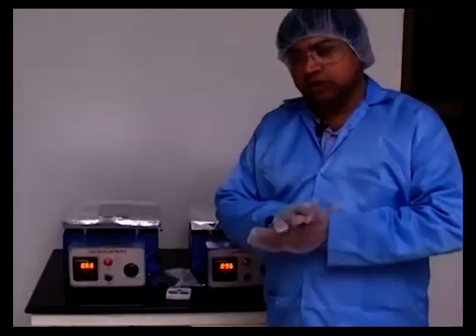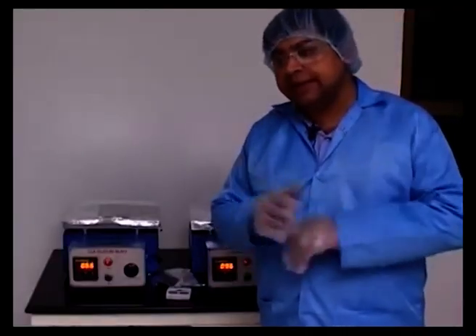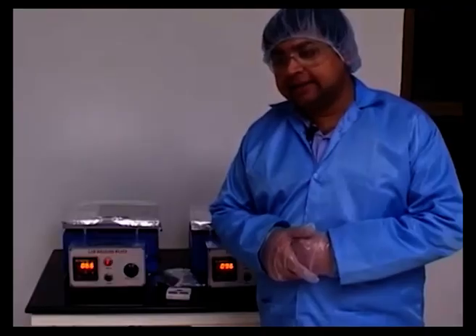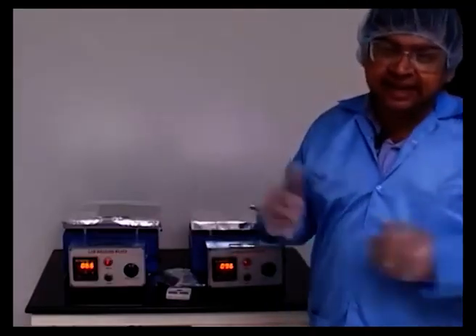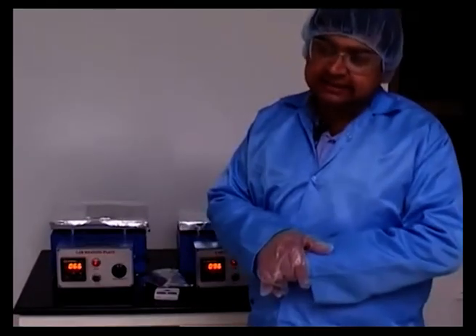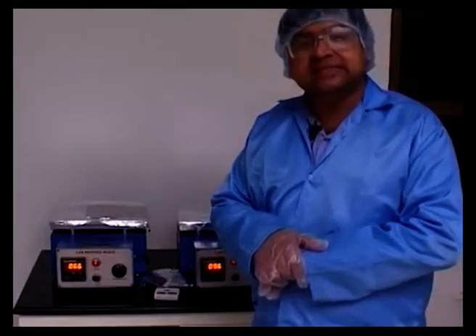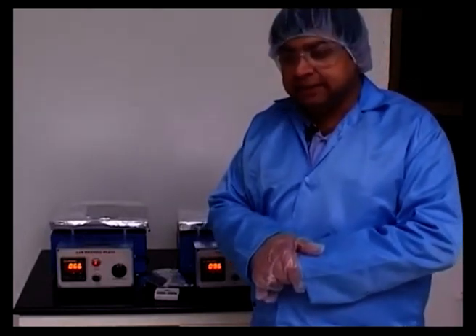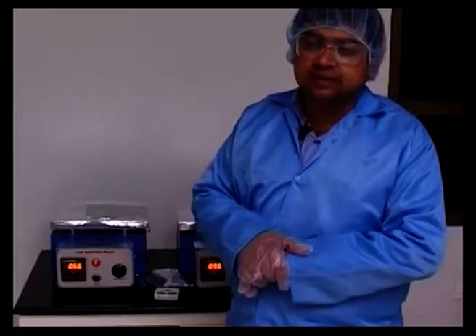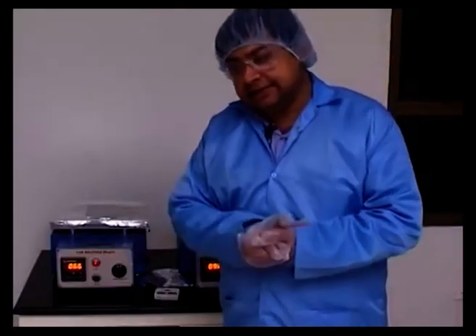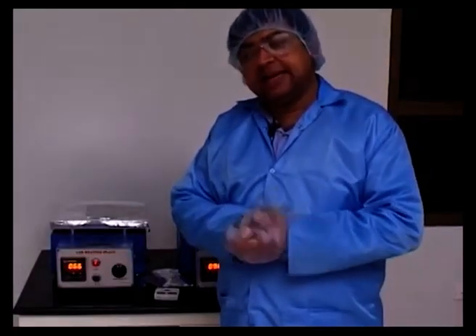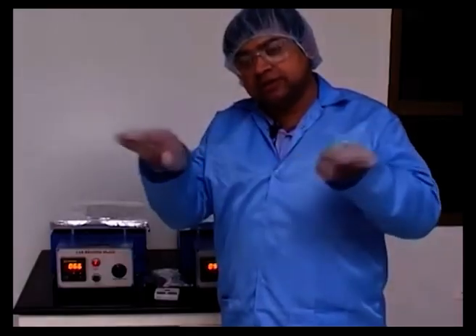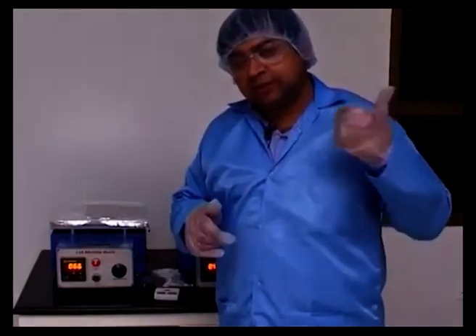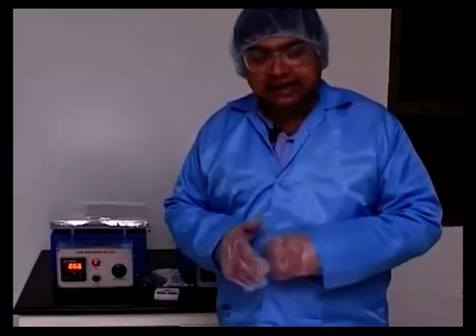So the resist, as I told you, needs to be heated, and one of the purposes why heating needs to be done is that there is a solvent which is really a carrier solvent for the resist. It has an epoxy resin which is dissolved in a carrier solvent, which is actually cyclopentanone, and essentially the purpose is to transport the epoxy uniformly over the surface of the wafer in the spin coating process that we saw in the last step.